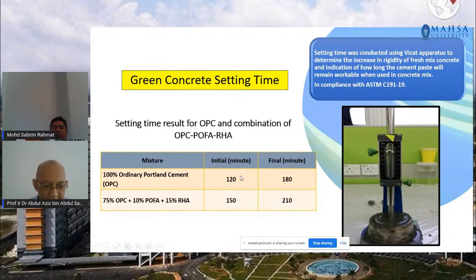So as you can see from this result, using our waste material of OPC, POFA, and RHA, the setting time is a bit longer as compared to the ordinary Portland cement. Ordinary Portland cement takes 120 minutes initially before it finally sets at 180 minutes. As compared to the green concrete, it takes 150 minutes initial setting, and by 210 minutes, only then it will have its final setting, based on the testing apparatus and its guidelines that we follow. So green concrete will take a longer time to set as compared to the ordinary cement. This is one thing that we have found out from our study.